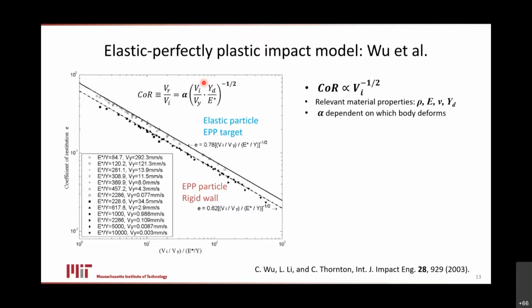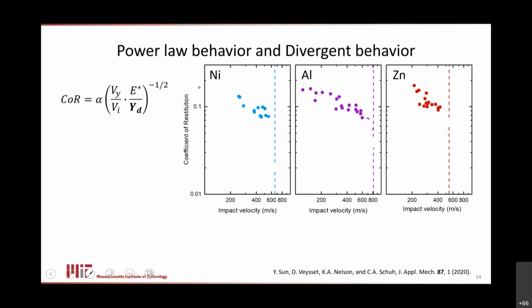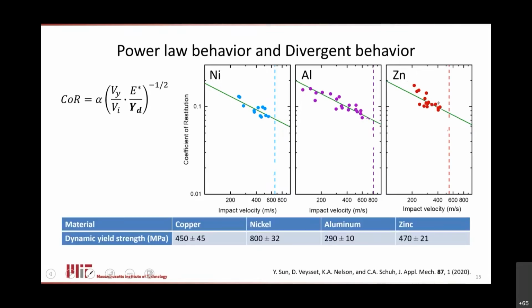But this model is really powerful because whether the target is allowed to deform or the particle is allowed to deform, all the data collapse onto a very simple and very beautiful power law. That power law holds over orders of magnitude of velocity. So we really have a useful tool now, because if we have a power law like this, it tells us what the effective yield strength is. And in fact, that's exactly the way it looks. When we do these experiments shooting metals at the same material substrate, we collect response curves which lie on that power law. So you can convincingly fit those data with this power law, and you can now extract from these tests what the prevailing yield strength is, or the average yield behavior describing the entire impact event.